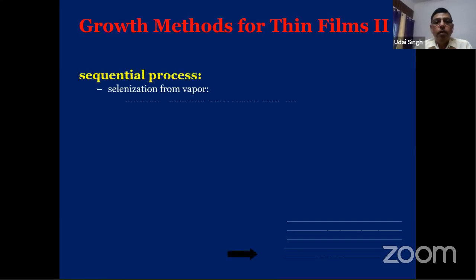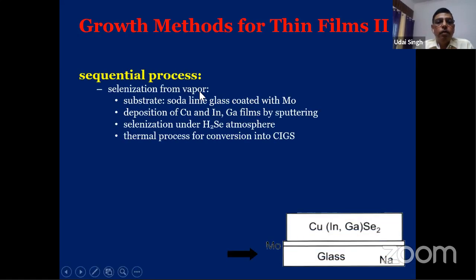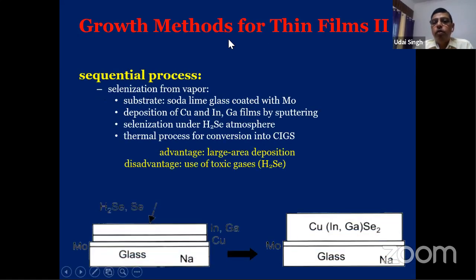Other method is the sputtering and selenization. So it's a sequential process, because you selenize from vapor. So you take the substrate, you deposit copper, indium, gallium by sputtering, and then you try to selenize with hydrogen selenide or selenium vapor. So large area deposition. Only disadvantage is hydrogen selenide is a very toxic gas.